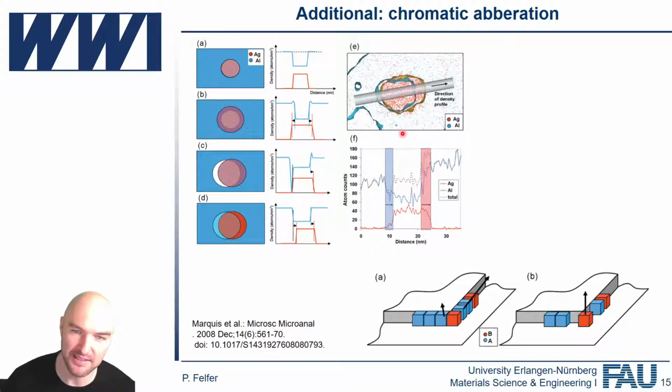But what that means is that if you are evaporating something that consists of more than one type of atom, then atom type A, in this sketch here, might come off easier than atom type B. What that means is that atom type B sees a little bit of a different electric field than atom type A. You know, just by a smidgen, just by a little bit, but it is selective to the actual atom.